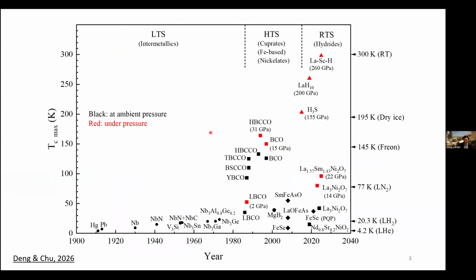I think many of us have different versions of the TC versus year map. That's the one constructed by Paul Chu and myself. Just looking at the TC increments since the discovery back in 1911, over those 70 years, we do see a very steady increase, but at a relatively slow rate. It's almost like a 20 Kelvin enhancement in the time frame of 70 years. I was told by Paul Chu that in those years, if you got only a few degrees enhancement, that was a great deal. So that was a very nice time to study superconductors in that respect.